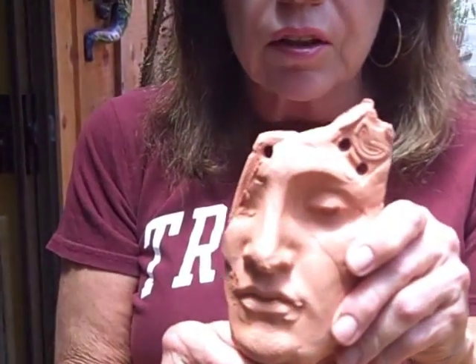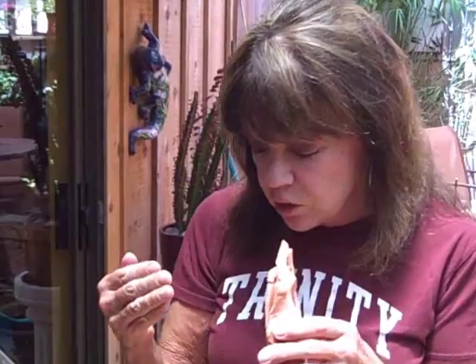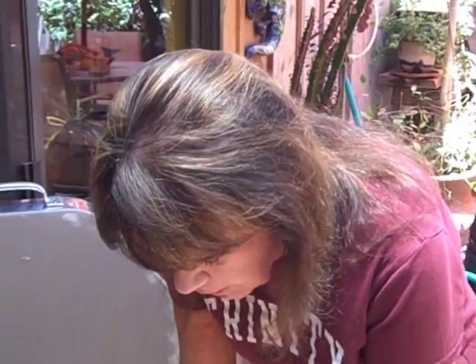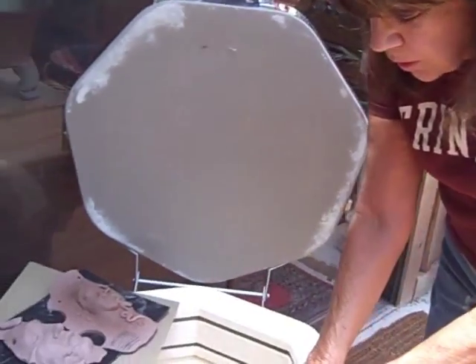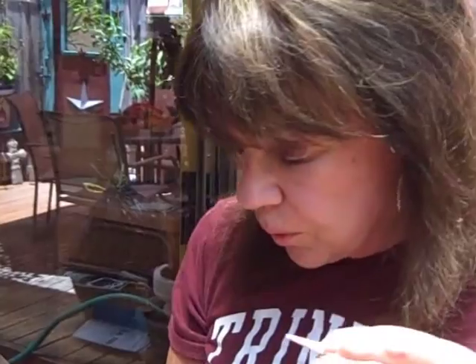This piece is what the clay looks like when it comes out of the kiln. This has been fired to cone 05 — that's 1888 degrees Fahrenheit — and you attempt to fire as close to that as you can. What helps you do that are these little pyrometric cones, which are made of the kind of clay that will melt exactly at that temperature, and that automatically turns your kiln off. Those of you who have used ceramic kilns before know all this, but it's not a difficult process.